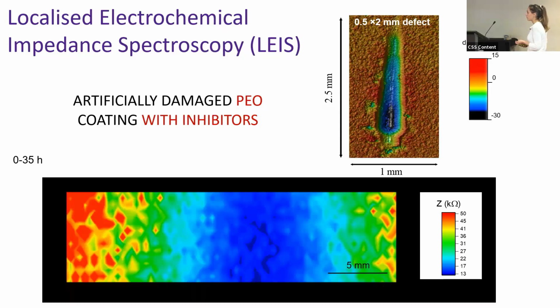This impedance map here corresponds to the vanadate specimen, and we can see here in the scale bar that red means high corrosion resistance and blue low corrosion resistance. So at the very beginning of the experiment, the corrosion resistance within the defect where the magnesium substrate was exposed was approximately 13 kilo ohm, while the corrosion resistance at the edges of the image was considerably higher, which corresponds to the coating.